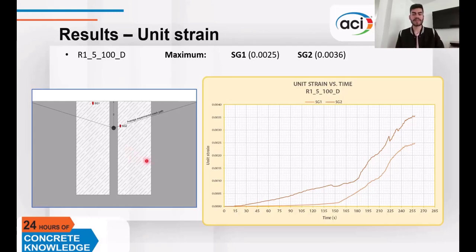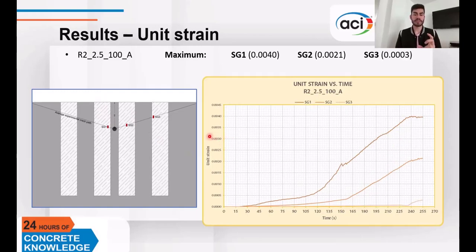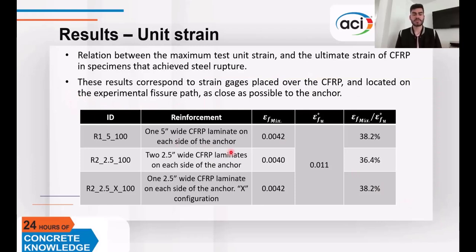Regarding unit strain behavior, strain gauges placed close to the anchor showed higher unit strains on the FRP than those located far from the anchor and the concrete breakout cracks. Here it is possible to observe that distributing the reinforcement into various laminates is ineffective, as these laminates do not show a significant strain. These are the relations between the maximum unit strain obtained near the anchor and the ultimate design unit strain of the CFRP, all calculated in specimens that achieved steel rupture. All the relations are similar, showing that given the steel properties used, the anchor failure occurs when CFRP is stressed to about 36 to 38% of its maximum capacity.